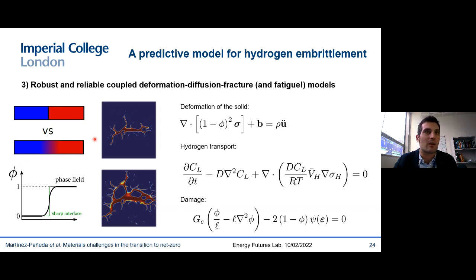And you can see it here. And by the way, I should emphasize here, I'm going to use the red color for plotting cracks. So every time you see red, that means a crack. And you can see, these are two different time steps, these very complicated cracking patterns occurring, crack coalescence, nucleation of secondary cracks, merging of multiple defects. So we can capture the propagation of cracks based on sound thermodynamics of fracture mechanics, and we have computational tools that will allow us to see how those cracks propagate.